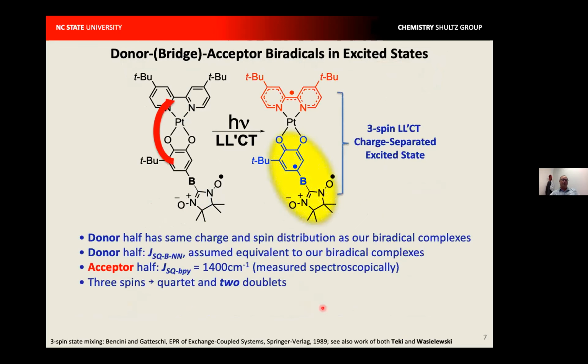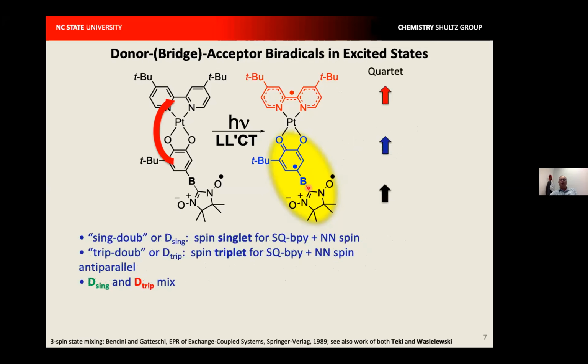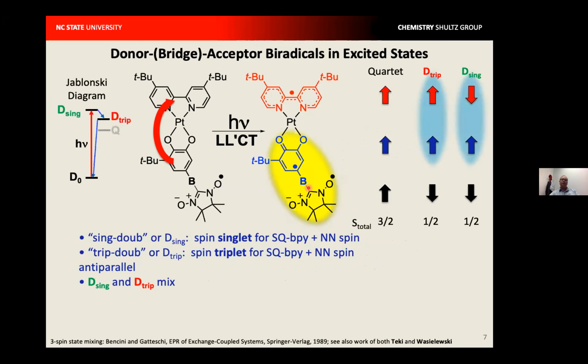When you attach a radical to these chromophores, you now have, as I mentioned in the introduction, a 3-spin excited state. And there are two dominant magnetic exchange interactions in this excited state, one between the semiquinone and bipyridine. We've actually measured that with magnetic circular dichroism spectroscopy, and that exchange coupling is 1,400 reciprocal centimeters, while the SQNN exchange coupling is mediated by the bridge, and we use the exchange parameters for our ground state biradical zinc complexes to evaluate that exchange parameter.